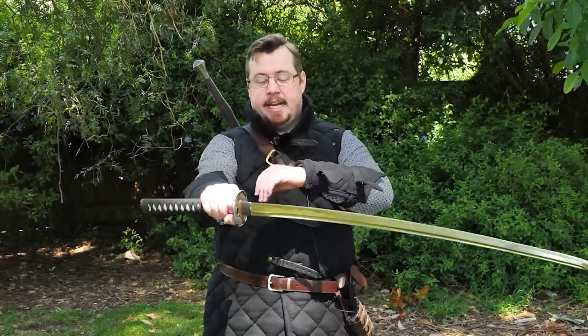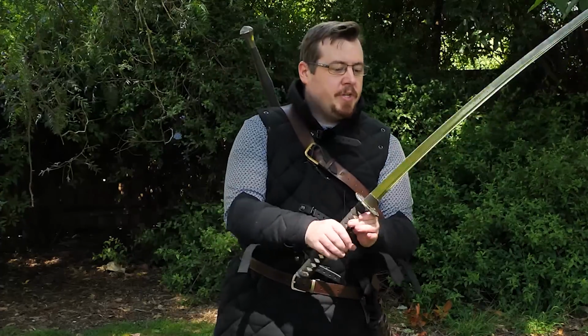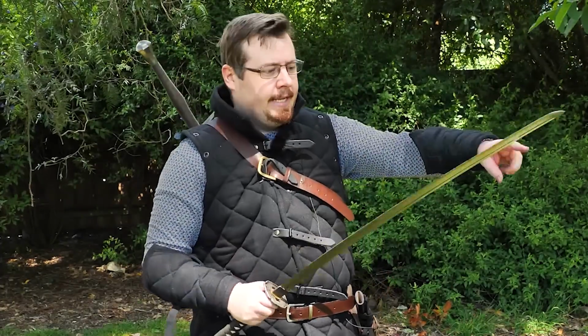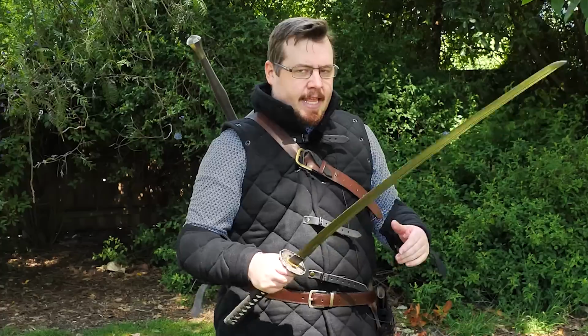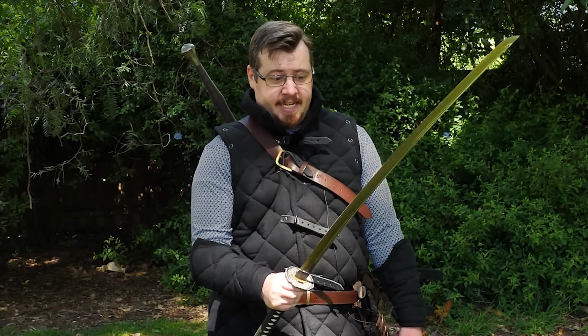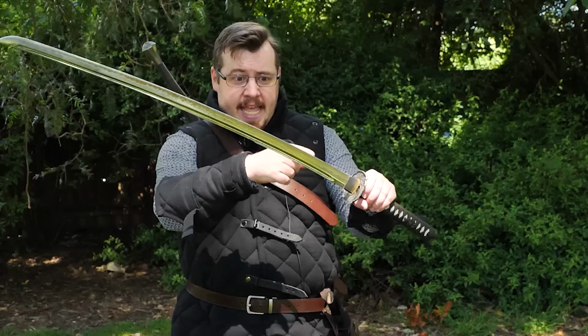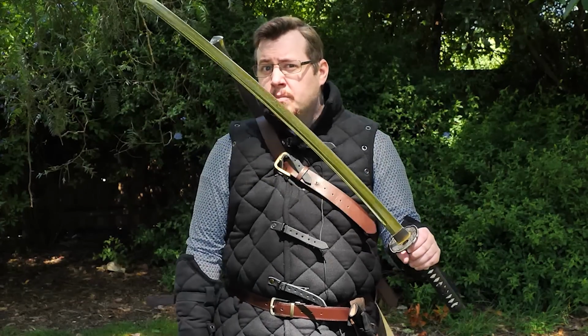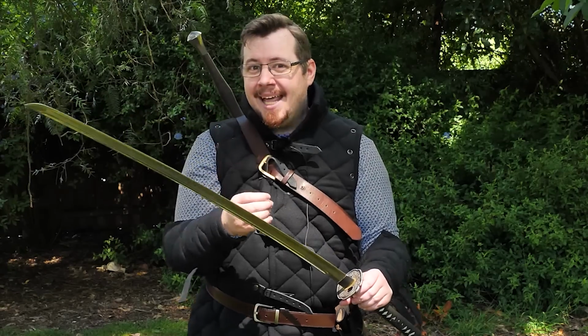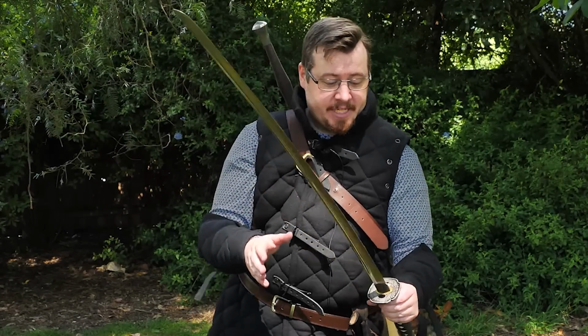the differential hardening that I was mentioning before. People assume that because the back of the katana is not as hard as the actual edge, that somehow makes it shock absorbent and therefore resistant to chipping and denting and breaking. That's completely incorrect. In actual fact, because the edge is so hard, it's more prone to cracks. The harder something gets, the more prone it'll be to crack instead of just deform and dent. So that's the first misconception to break.